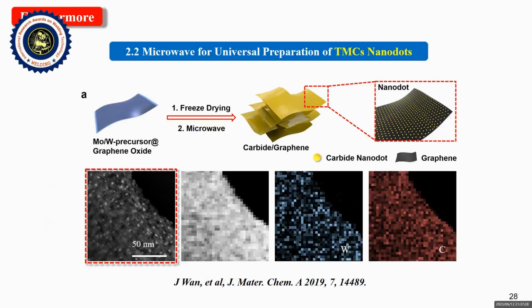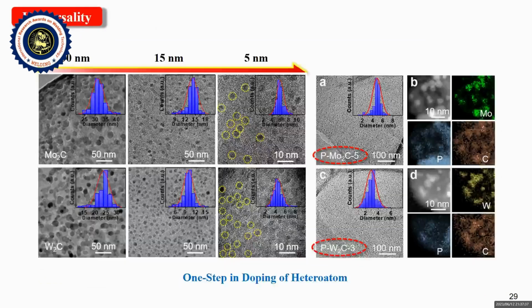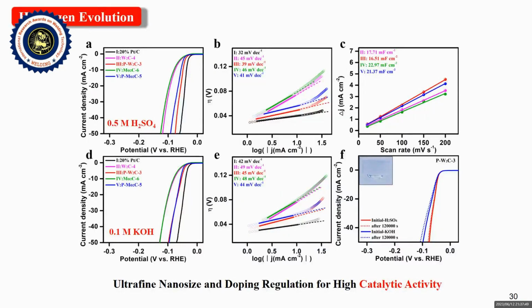Furthermore, in addition to ordinary nanoparticles, we can also use microwave to prepare ultrafine carbide nanodots. Because of the universality of microwave, we can also do one-step doping. This ultrafine size and doping regulation could exhibit high catalytic activity in hydrogen evolution. So next,